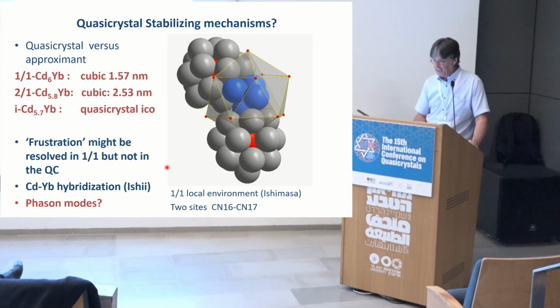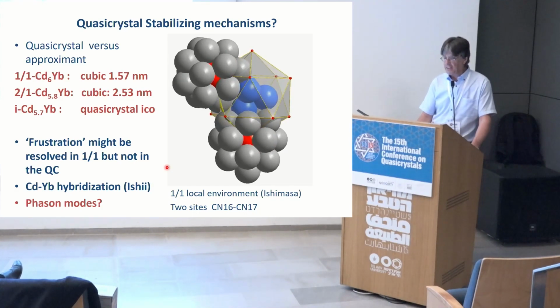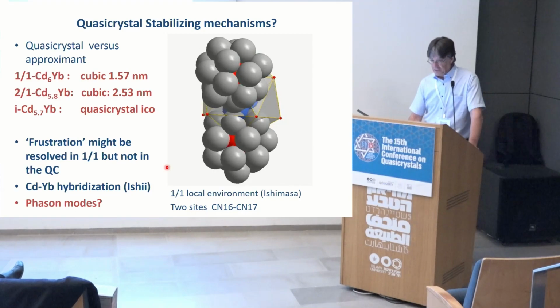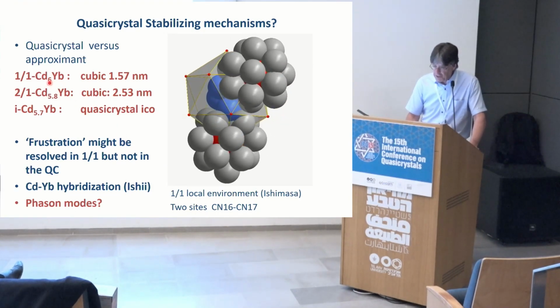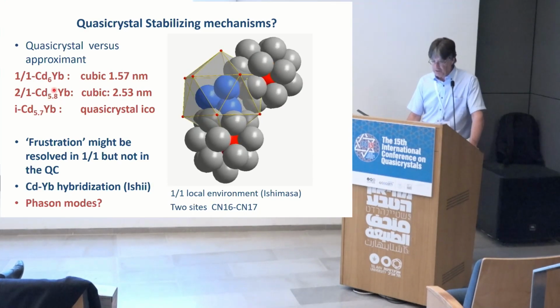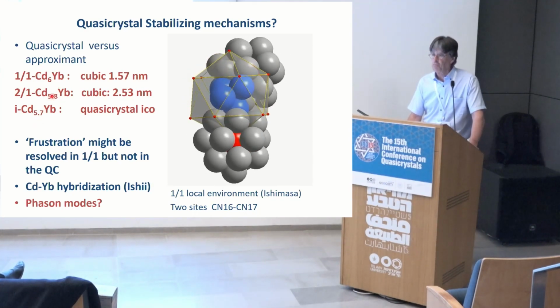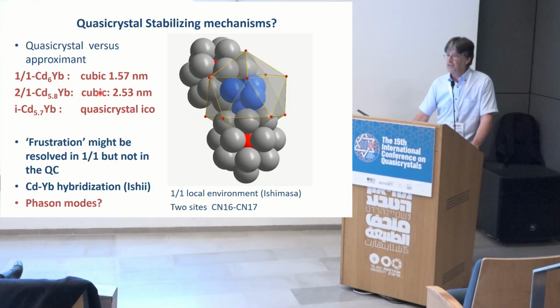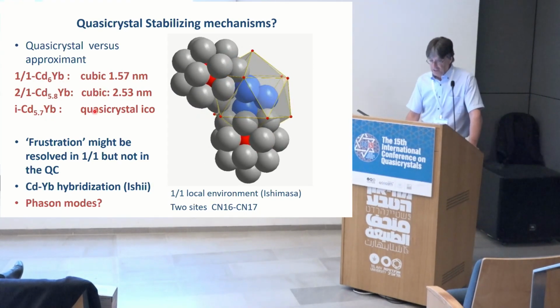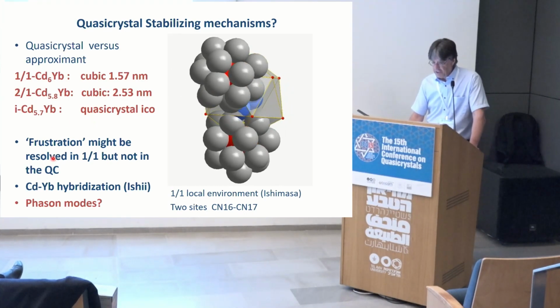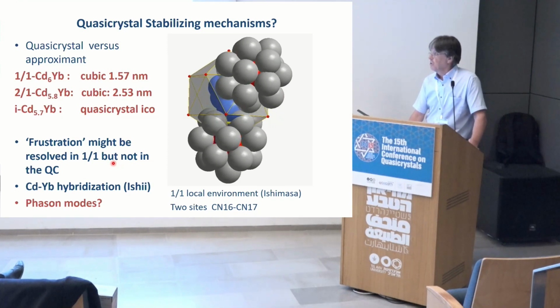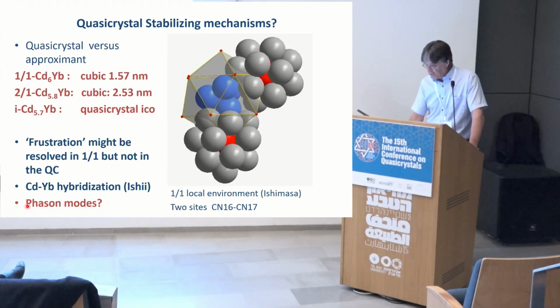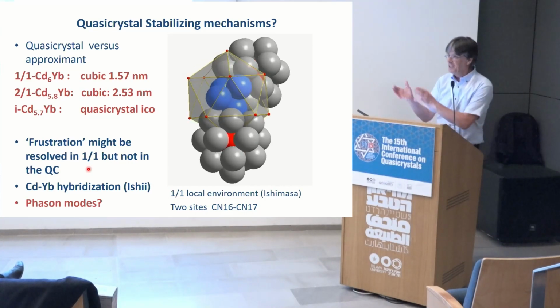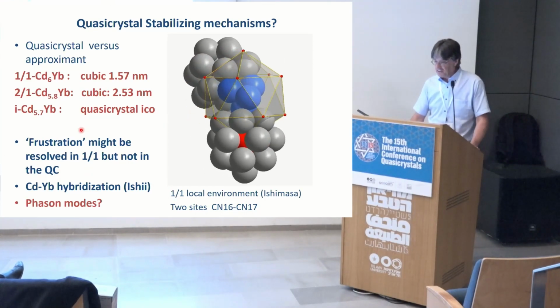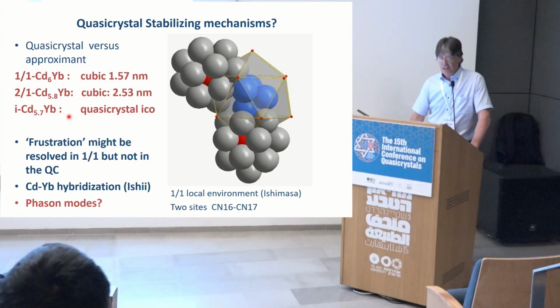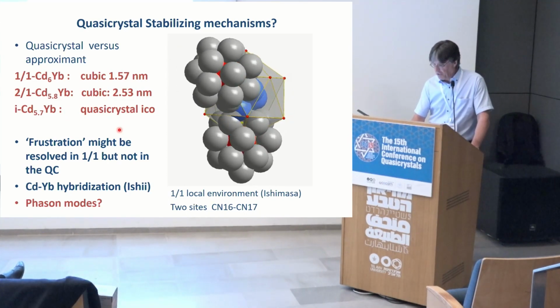So just to finish, I think there is one fascinating question: what are the mechanisms that are stabilizing quasicrystals? And why is it that if you go from cadmium 6 ytterbium to 5.8 and 5.7, so you see here it's really a tiny difference in composition, you go from a periodic crystal to a quasi-periodic crystal. Frustration is certainly a key ingredient. Electronic properties are also an ingredient. I do believe that the phason mode is playing a role, but still to be proved in this particular system. But I think it's still fascinating, and there are a lot of things to be learned about that.